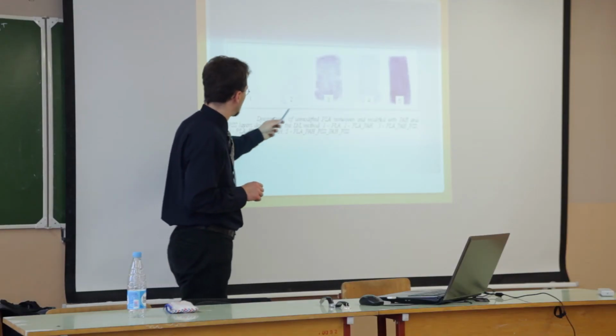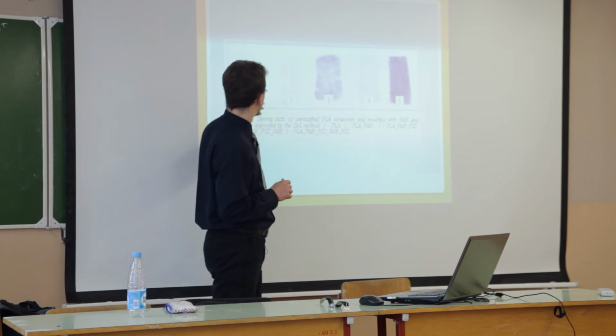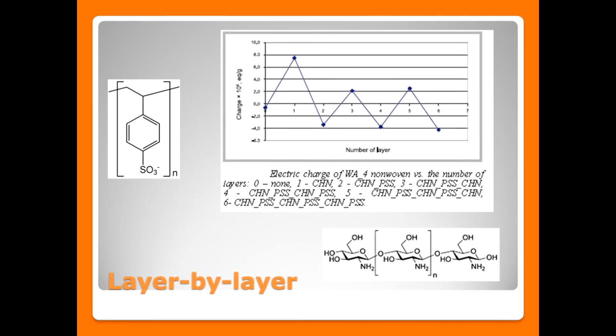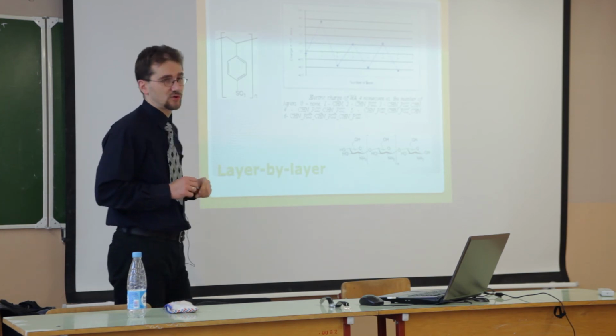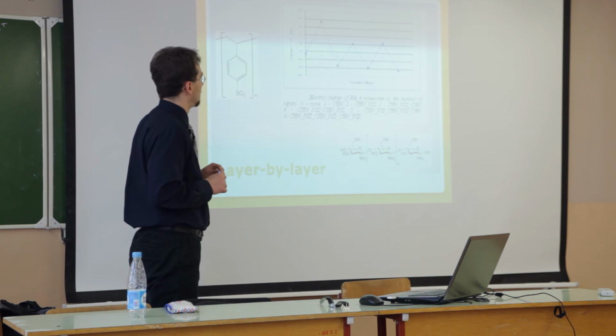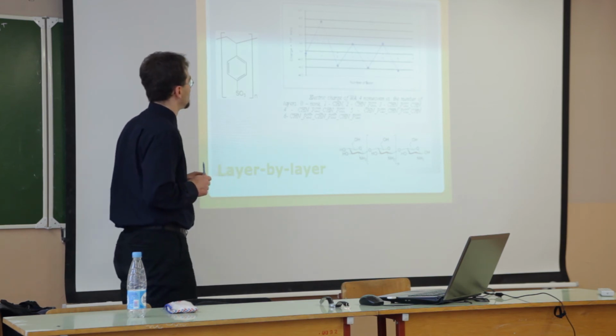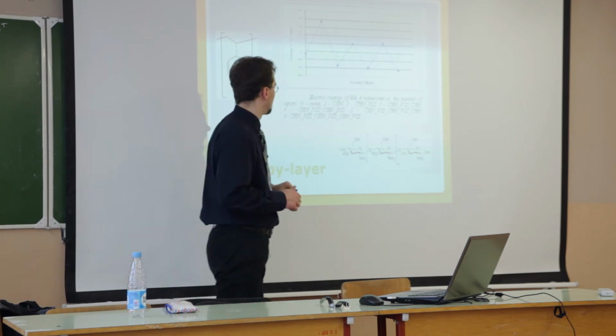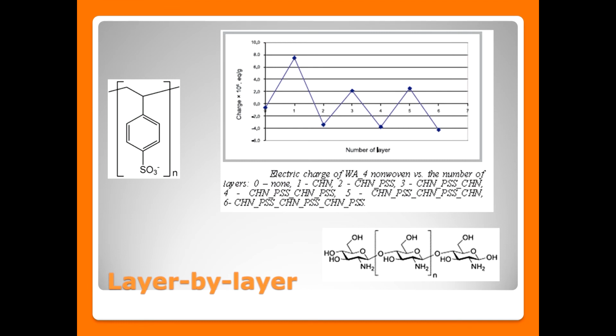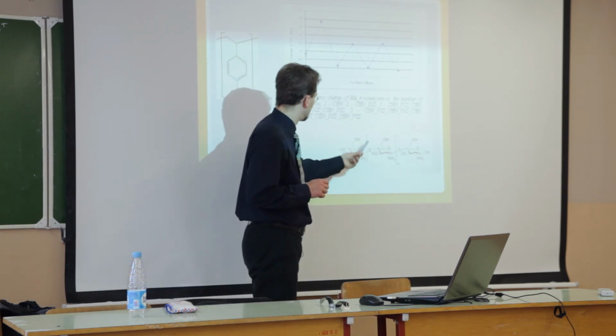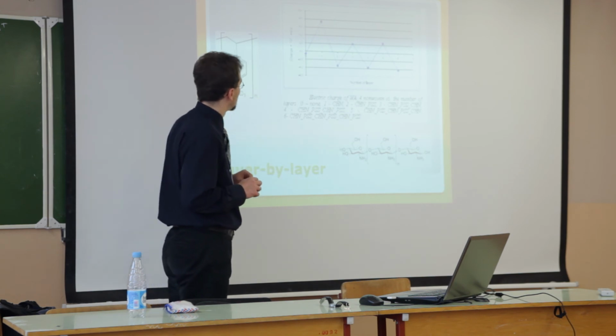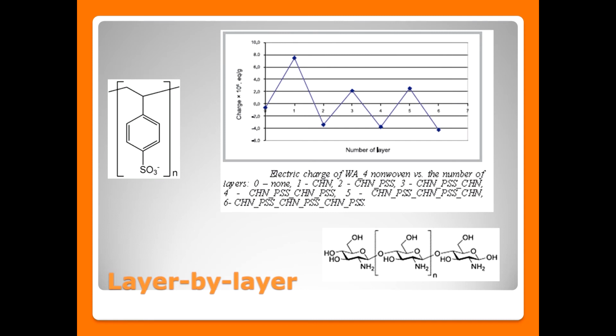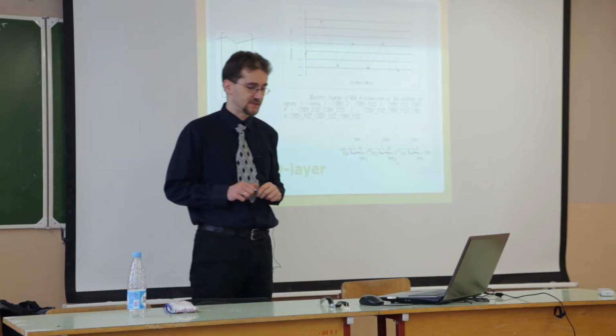Here we used polystyrene sulfonate instead of polyacrylic acid, and again it's white, blue. Such a relation is possible for different layers, and we also controlled the structure using electrical measurements. For example, the charge depends on the number of layers. This is a different example: negatively charged, using polystyrene sulfonate, and positively it was chitosan, and again there is such a relation. When it looks like this, it means the modification was effective.